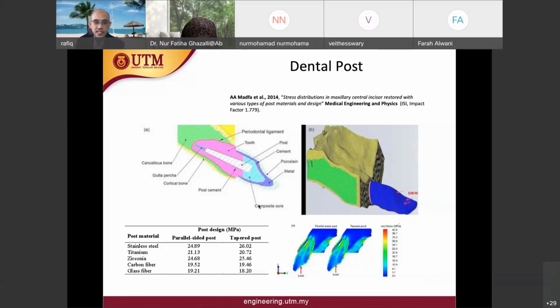So normally they just use either stainless steel or titanium, and so we analyze using computer simulation the post design with different materials. The post design is either the parallel sided post or the tapered post. So that's the design that we have for the post, and then we vary the materials of the post. We compared 5 different materials: stainless steel, titanium, zirconia, carbon fiber, and glass fiber. These are not functionally graded materials.